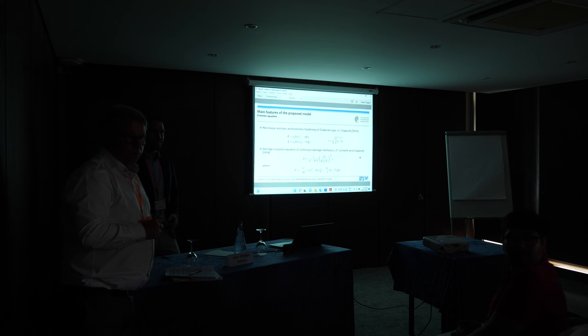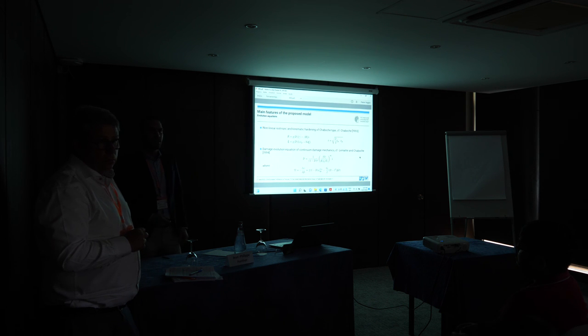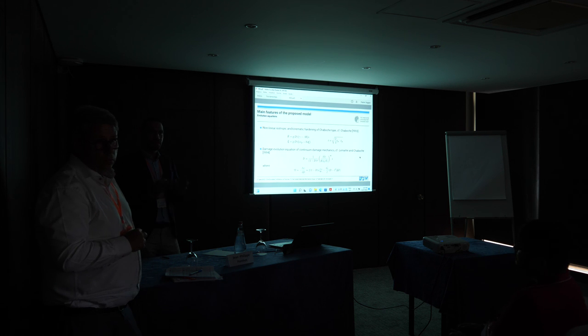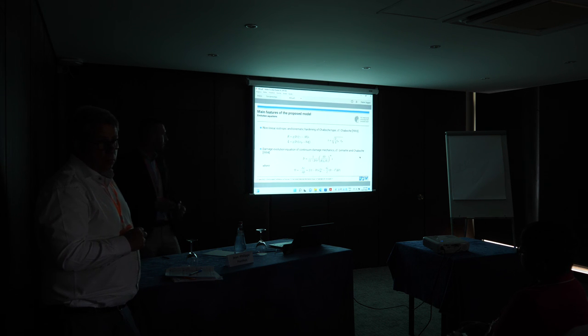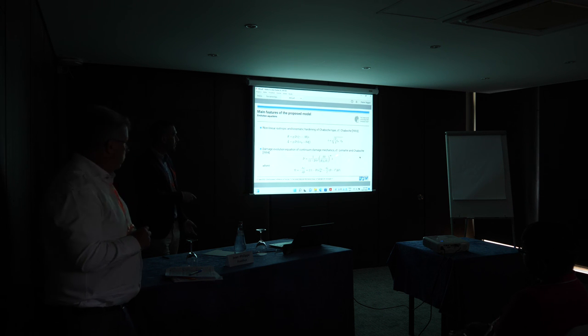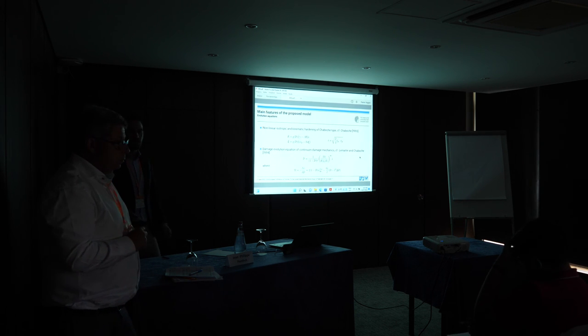One question regarding the plasticity model: it is a local model, so there is no gradient in the plasticity. Would it be possible to extend it to include gradient plasticity? Yes, of course. The plasticity part and the damage part are largely independent from one another, besides the fact that damage evolution is coupled to the accumulated plastic strain rate. Since it is the accumulated plastic strain rate, independent of how it is accumulated, one can also use a gradient plasticity model.